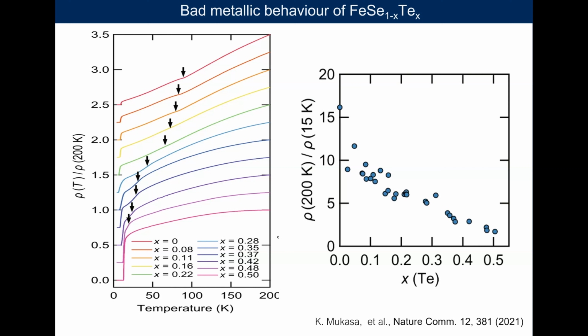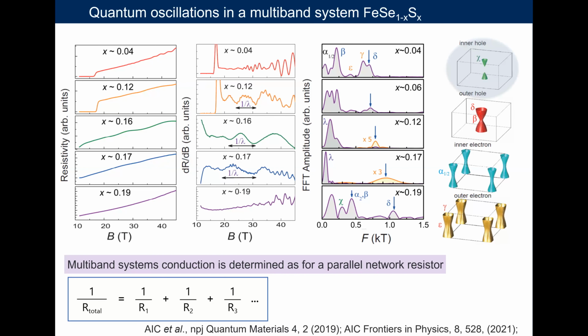But on the sulfur side, we have very good metal, and we can see beautiful quantum oscillations. And these are some of the data in magnetic fields as we change the substitution. So this is the 4% substitution, 12%. And as we increase substitution, what we notice is that this oscillatory spectrum, which is complex because we have a multi-band system, seems to become dominated by a low frequency. And we can start seeing that this low frequency gets stronger and stronger, and eventually it disappears together with the nematic phase. So why could this low frequency occur?